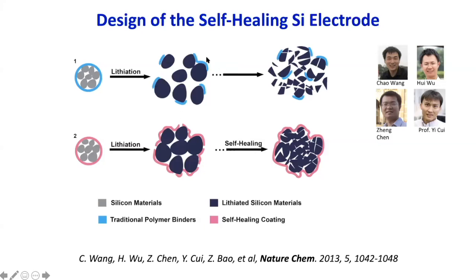And the polymer around them, people typically have been using rigid polymer before, because for carbon electrode, there is hardly any volume expansion. So they don't have to worry about the volume expansion issue. But using those polymers in the case of silicon, they will break apart as well when the silicon particles have large volume expansion. So that's when, almost 10 years ago, we started working with Professor Yi Cui's group.